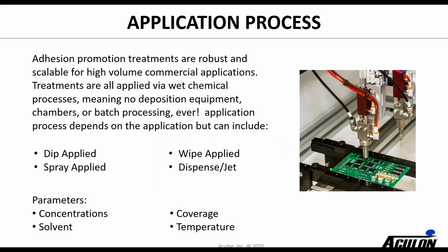So as Edward spoke to, this application process has a lot of advantages. It's a liquid applied process, so you can think about it either being dipped, sprayed, wiped, dispensed. All of these things can be done in a continuous fashion, which is important, because from a cost standpoint, processing in batches is sometimes a lot more expensive. So you can set up continuous treatment lines, and the main parameters we look at for the actual chemistry are concentration of the actives, what types of solvents we're using, and where we need to cover the part. Most of the time, our primers can be applied at room temperature, but there are some substrates that do require a cure.